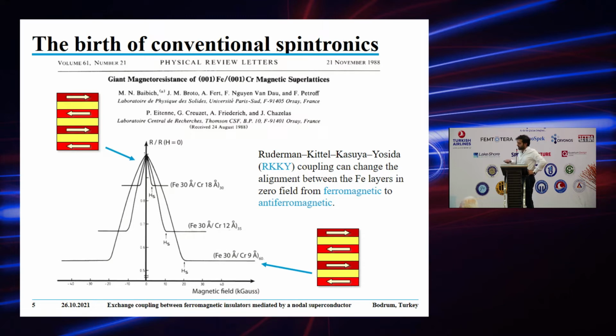What they discovered is that they grew multilayers of iron and chromium, and they realized that for a certain thickness of the spacers, in this case the chromium layers, it is possible in zero field to have the magnetic layers, the iron layers, coupled antiparallel. When the applied field is very high, the iron layers point parallel to each other. I made a mistake here, so all the arrows should be pointing in the same direction, and the resistance is minimum.